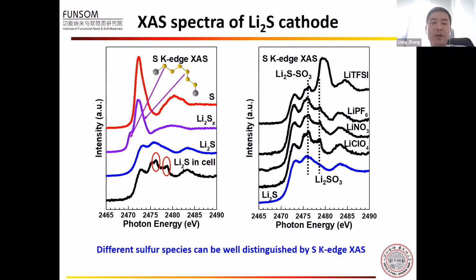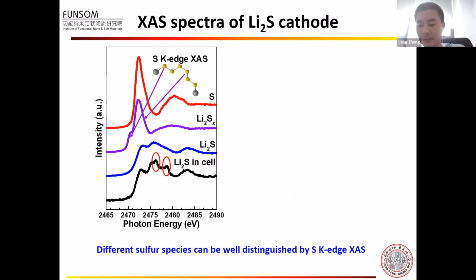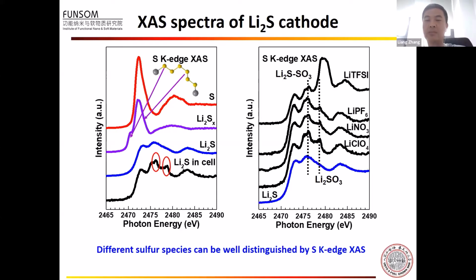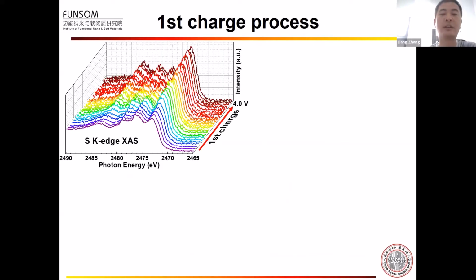To confirm this, we also measure the lithium sulfide contacting with different lithium salts, including lithium perchlorate, lithium nitrate, LiPF6, and LiTFSI. We always find the oxidation peaks, and lithium perchlorate shows the strongest oxidation peak, indicating lithium perchlorate has the strongest oxidation ability. From this result, we can clearly see that the different sulfur species can be well distinguished by the sulfur K-edge XAS. We therefore perform the in-situ sulfur K-edge XAS.